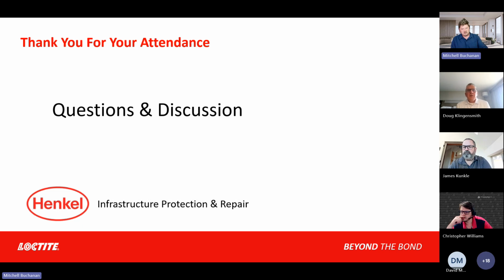So if you do need a structural repair because you've got wall thinning or blistering, or in the case of HDPE, you might have micro cracking, developing stress cracking, then a composite type solution is probably more appropriate if you're going to repair in place. Which might be one of those Clock Spring NRI solutions. Yep, depending on what we find out, David. And potentially DuraShield if you don't need the structural repair, but you want something with high tensile strength.